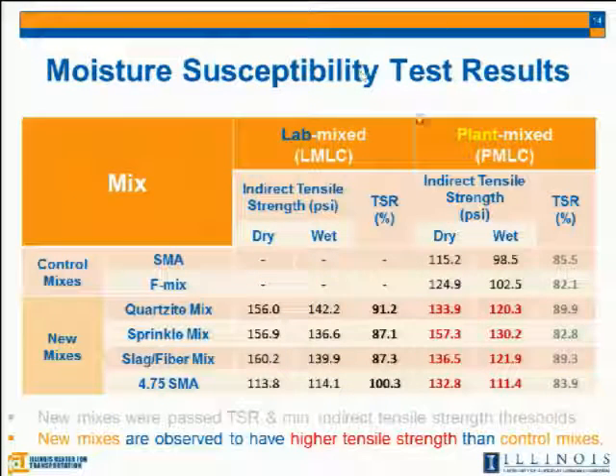But the TSR value from the plant mix. After we sample the materials from the plant, to make a gyratory sample we reheat the materials and then compact. So in that case, the property of these materials or something happens in the mixture. Even though you can see the 82 or the 83.9 didn't satisfy the threshold, this is the reheated materials. So we didn't take care of this TSR value from the reheated materials. But to compare the IDT strengths, we use this number to compare our new mixture to the control mixture.